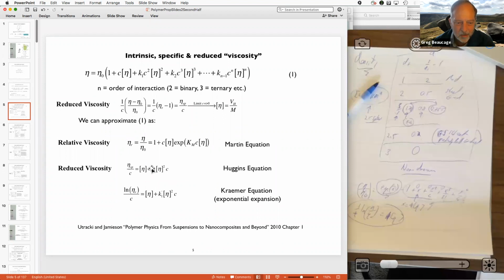That parameter will reflect the interactions between the polymer chains, right? So in the context of a flow experiment, it's not the thermodynamic interaction like 1/2 minus chi, although it's related to that. It's the interaction under a certain shear rate. So this number could change with shear rate. In other words, how fast you pump the fluid through will change that number.